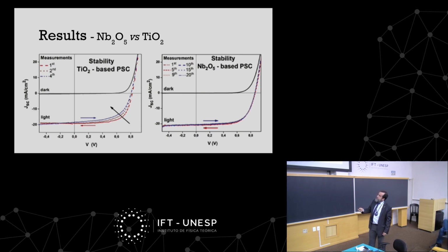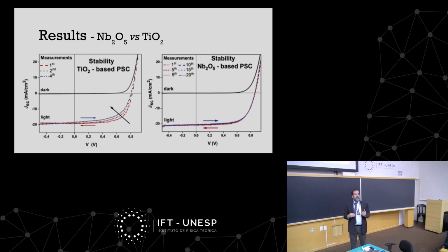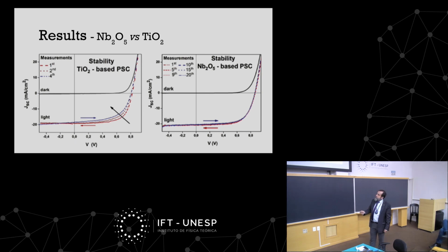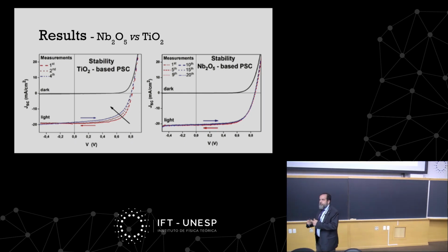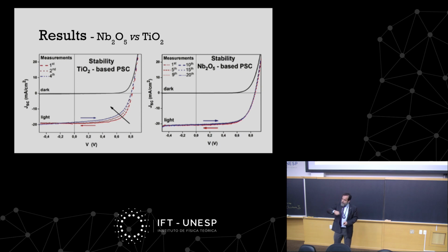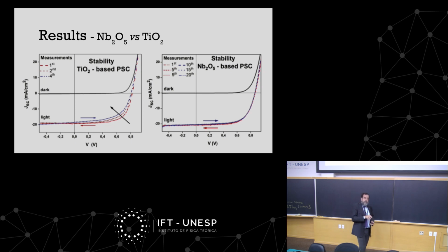And as you can see here, I am making several measurements, one after the other. The first measurement is this red, and the fourth measurement is this blue. And what is happening? I'm losing area. Each time I make a new measurement, I'm losing area, which means my cell is degrading. My cell is losing its conversion power. But more intriguing in this material is that depending on how I do the measurement, going from low voltage to higher voltage, or from higher voltage to lower voltage, I don't get exactly the same curve. That's why we talk about what is called hysteresis, because it depends. Just like hysteresis in ferromagnetism, if I go and I go back, I don't get exactly the same. So I have a hysteresis.